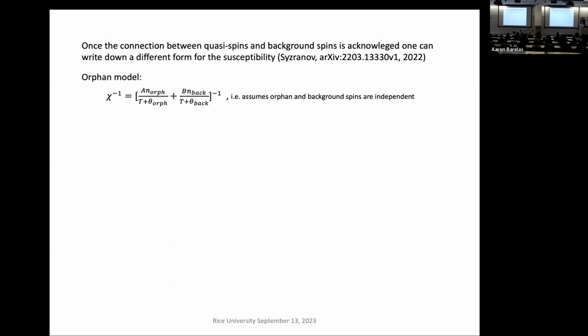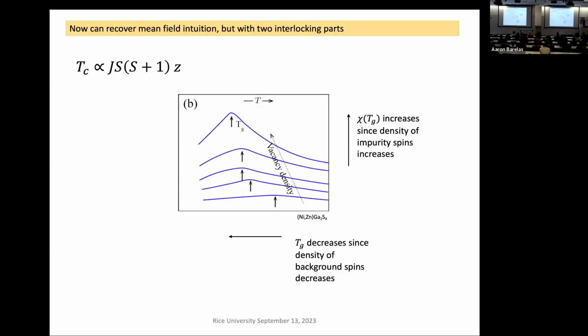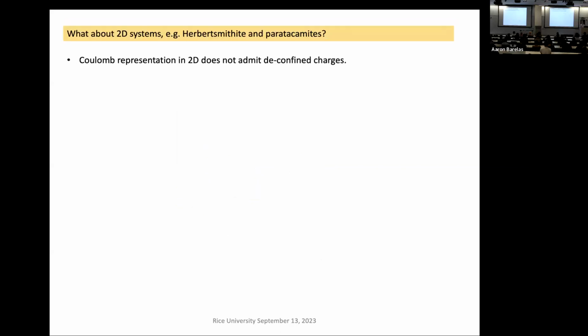Okay, so once the connection between quasi-spins and background spins is acknowledged, one can write down a different form for this susceptibility. Instead of the orphan model where these two terms, the background and the upturn, are independent, we make them dependent, as you should, right? Because if you put vacancies in, then you're taking spins out of the background. So the simplistic notion of what's happening is that what's controlling the collective degree of freedom is basically a percolation phenomenon of the short-range order in the pure system, but what's controlling the size of the signal is the number of spin vacancies.